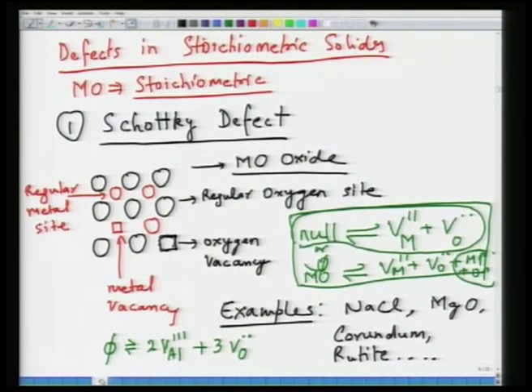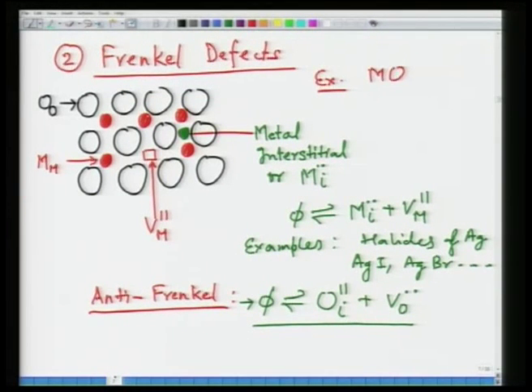So, the first important defect is the Schottky defect. Schottky defect is nothing but formation of a metal and oxygen vacancy, simultaneous formation. This does not disturb the stoichiometry of the material. So basically you have a pair of two vacancies in a given solid. Of course, the relative proportion of these vacancies will change if you had materials like Al2O3 or TiO2. I would leave it to you to work out, but make sure that you maintain the charge and site balance there.